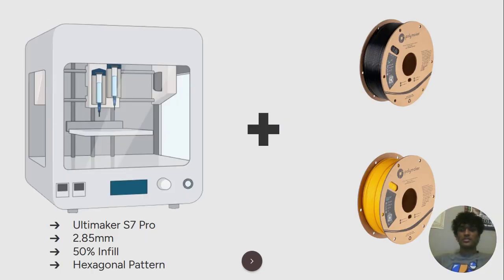This file was then printed using an Ultimaker S7 Pro printer, and the following constants were kept. For each prosthetic printed, the brand Polymaker was used for ABS and PETG filament with a diameter of 2.85mm. Additionally, a 50% infill and a hexagonal pattern was implemented, meaning within the actual plastic itself, it was 50% full, meaning a 0% infill would mean that within the actual structure of the plastic, it was 0% full.